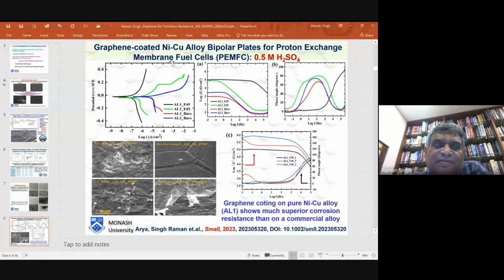Also, we developed graphene on nickel copper pure alloy, and we got extraordinary corrosion resistance in sulfuric acid. It's a highly aggressive solution, but this data is quite applicable for this kind of fuel cell, proton exchange membrane fuel cell. Their bipolar plates have a very demanding situation, and in this environment, there is very little corrosion damage. Again, it is a polarization plot where the intercept of the two arms gives me corrosion resistance.